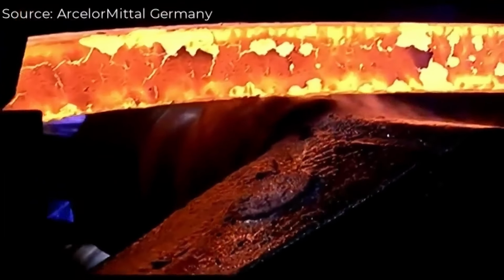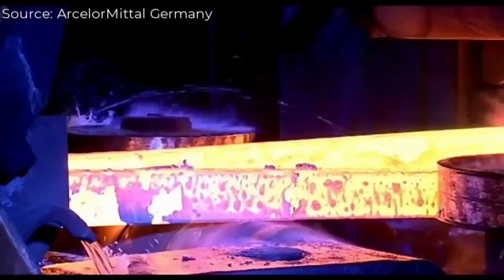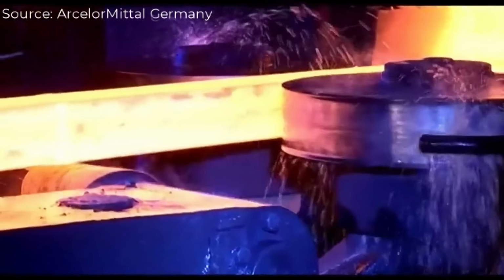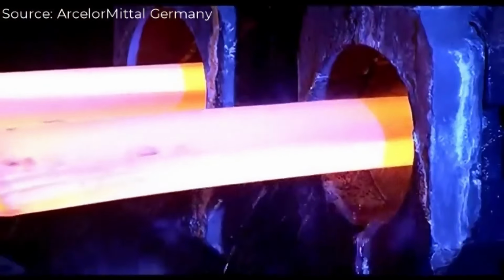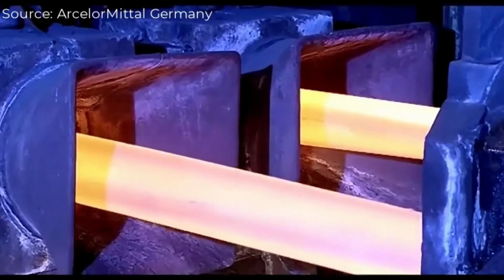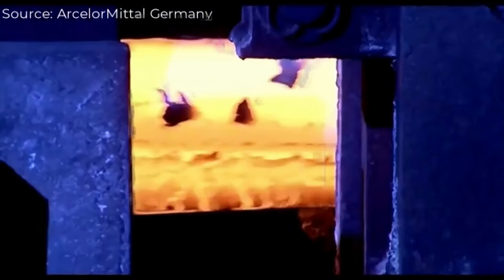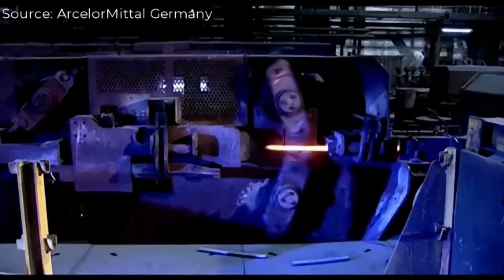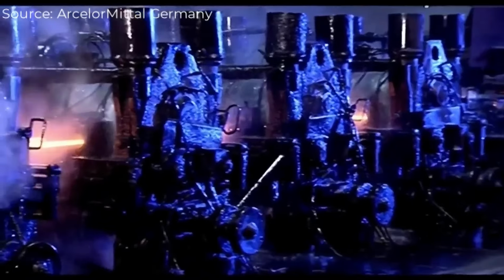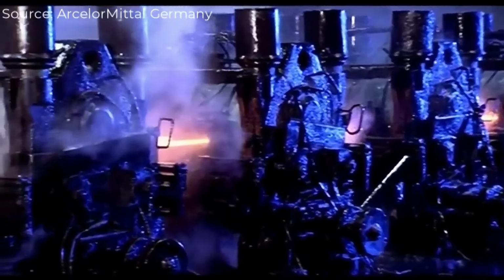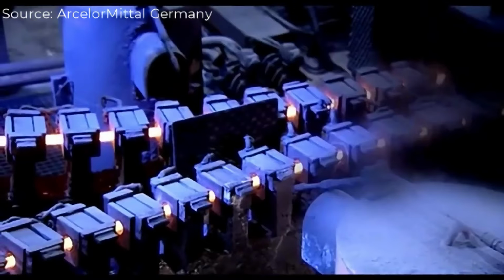The billets are further heated above 1000 degrees Celsius, then hot rolled through multiple stations, gradually reducing the size to steel wire, with a diameter of 5.5 to 16 millimeters. The wire is coiled into rings at speeds of up to 100 meters per second, cooled in a controlled manner on a conveyor belt to shape the mechanical properties.